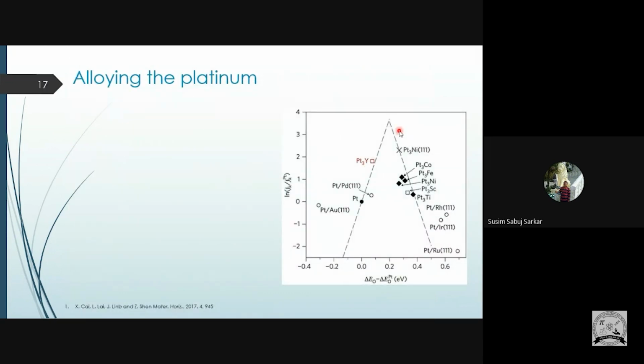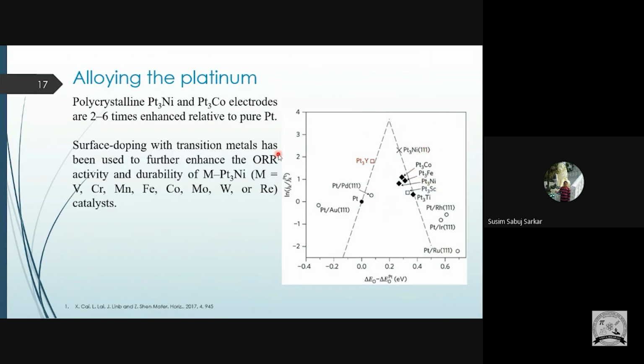So these are what people have tried. People found that Pt3Ni gives one of the highest activities we can get. There is also the 111 facet, which means only this form gets high activity, not the other forms of platinum nickel. Also, with platinum nickel, people want to enhance the durability of the material, because platinum is not very durable.